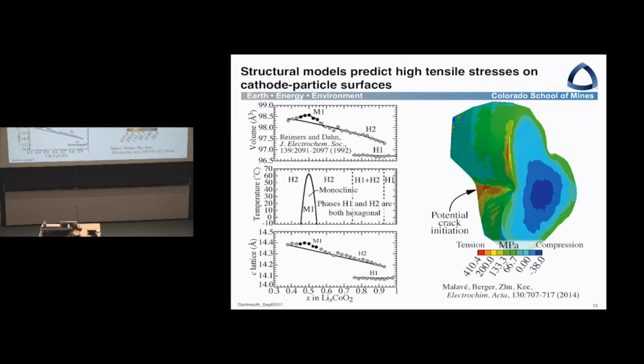I take two slides here as a little bit of a detour, but actually at least an interesting detour. So this is in the chemical-mechanical coupling. Here is a lithium cobalt oxide particle that we've extracted from this three-dimensional structure I showed. We just extract an individual particle and intercalate it. What I'm showing here, actually rather old data from Reimers and Dahn, shows that as you intercalate lithium into this cobalt oxide, at first there's a monoclinic phase, then there are actually two hexagonal phases as you intercalate, or as you reverse back in the case of charging.